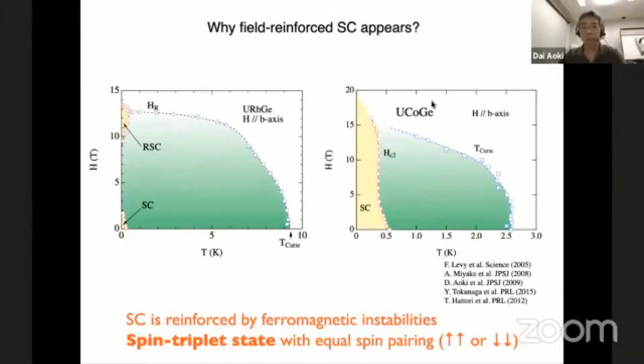Again, uranium cobalt germanium also shows a similar behavior. So the Curie temperature is suppressed, then the S-shaped field-reinforced superconductivity is observed. This shows that when the Curie temperature is suppressed, ferromagnetic instability is strongly enhanced. Ferromagnetic fluctuation is strongly enhanced. Then the reentrant superconductivity is observed. So now I want to switch to uranium ditelluride.